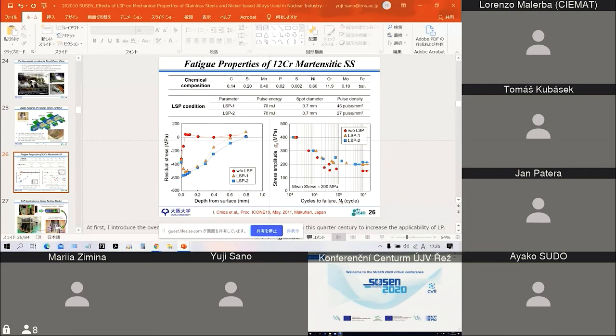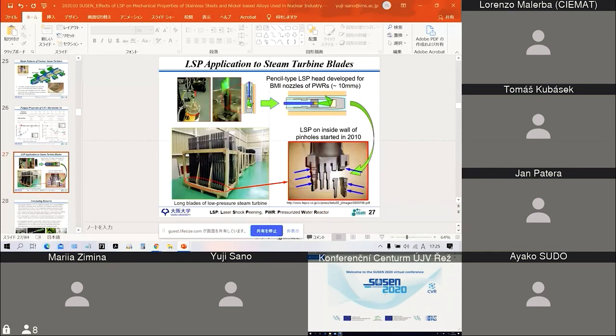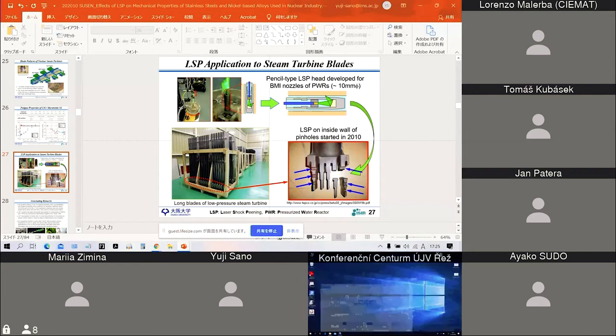So we constructed a system to apply the LSP system to the turbine blade, especially for the inside wall of the fork part. Actually in Japan, we experienced the drop-off of the turbine blade due to a fatigue crack initiated from the inside wall. So that's why we developed a very small optical head similar to that for the PWRs, and peen the inside of each hole of the long turbine blade.